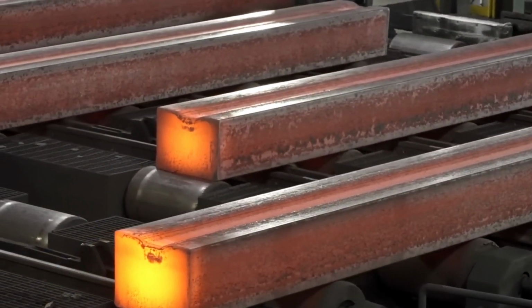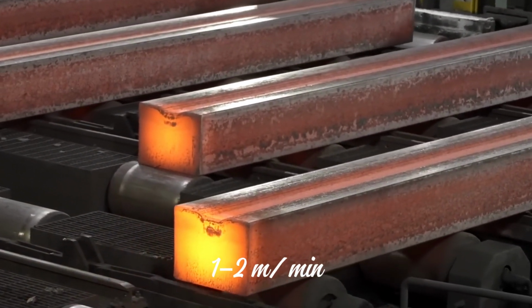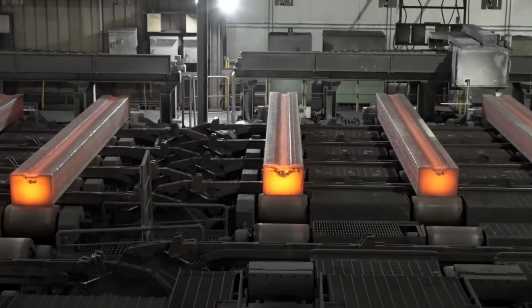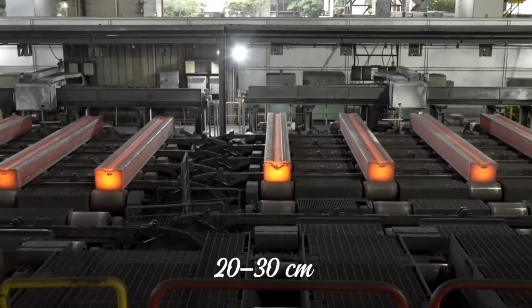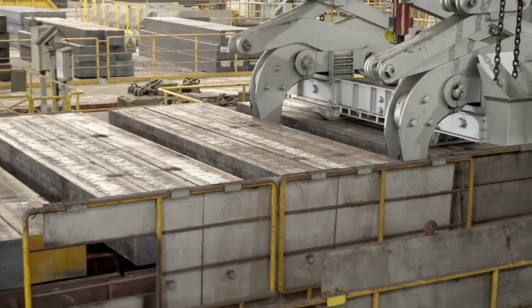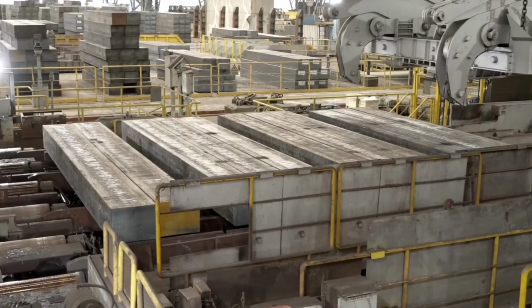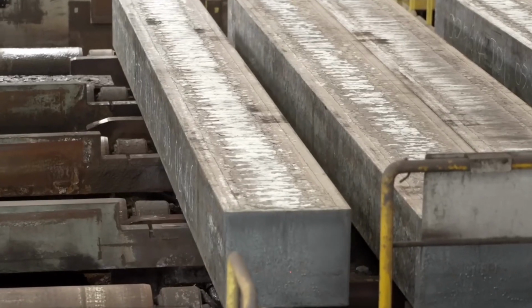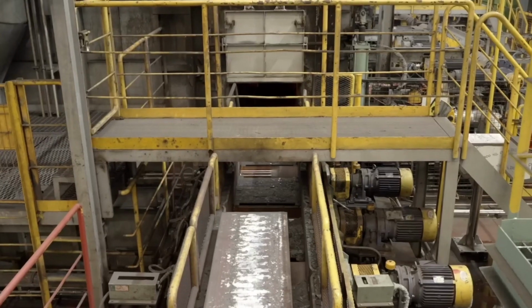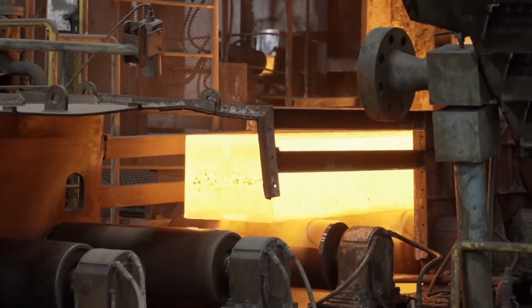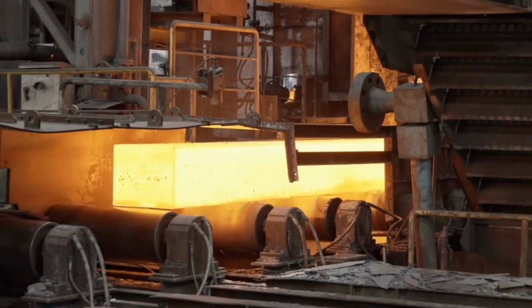Rollers pull the slab down at 1 to 2 meters per minute. Spray cooling grows the shell to 20 to 30 centimeters thick. If withdrawal speed exceeds cooling rate, internal cracks. If cooling is uneven, surface tears. Continuous casting is controlled moving solidification, not simple cooling.